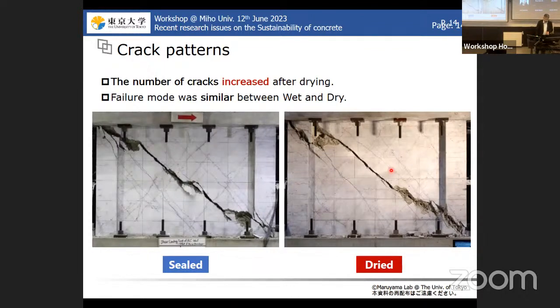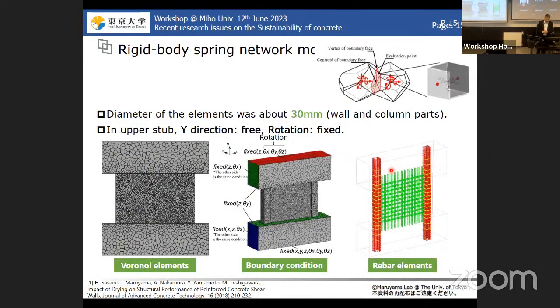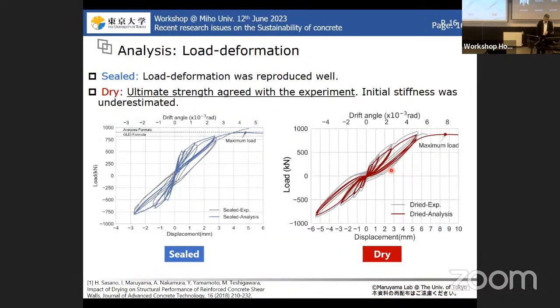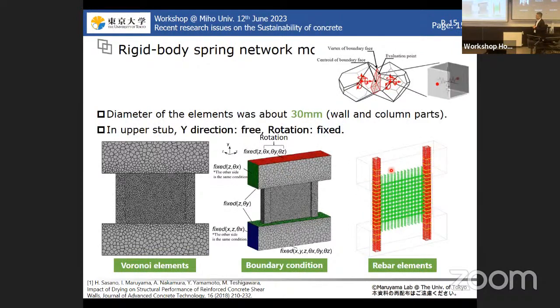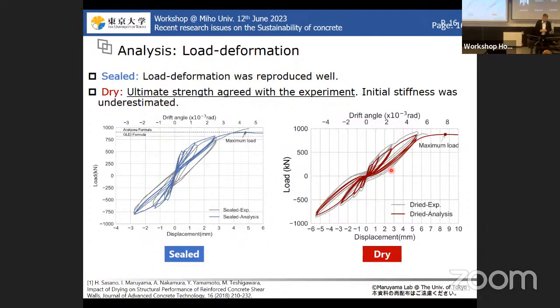And I tried to calculate some structural things. I briefly would like to introduce what I have done. So based on the rigid body spring network, we try to reproduce the structural performance of this reinforced concrete structure. And the cyclic pattern is quite close, and the ultimate strength is almost the same, but the deformation at the loading capacity is a little bit shifted. That was reproduced by the numerical calculation.